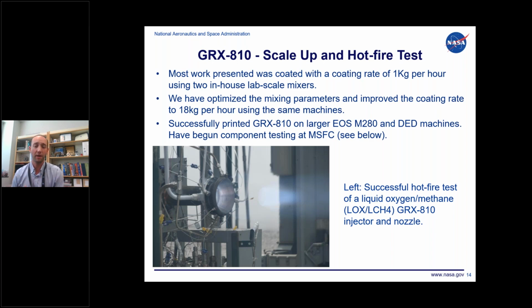I do want to talk about this coating process. When we started, we were coating about 1 kilogram per hour in our in-house lab scale mixers. We've been able to now get another mixer, but also optimize the coating process so that we can more or less have a coating rate of 18 kilograms per hour. We really do feel that this coating process we've been using for GRX-810 is very robust and can be further scaled to maybe introduce other oxides.